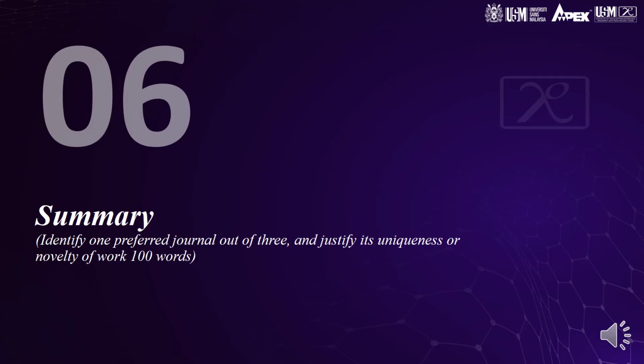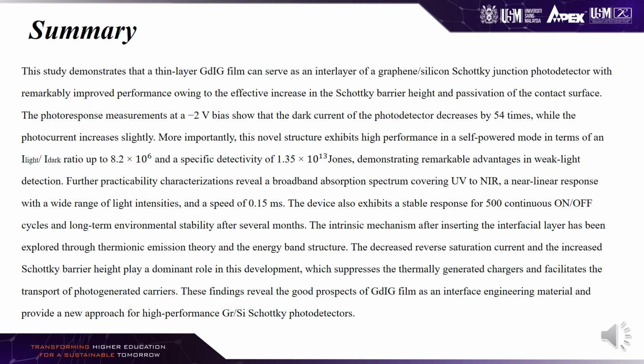This is a summary for one preferred journal. The first journal is chosen based on this summary. This study demonstrates that a thin layer gadolinium iron garnet film can serve as an interlayer of graphene silicon Schottky junction photodetector with remarkably improved performance owing to the effective increase in the Schottky barrier height and passivation of the contact surface.